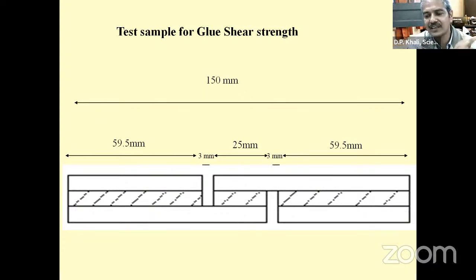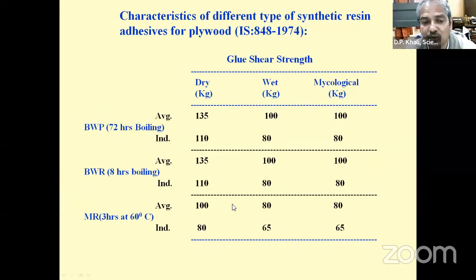In the previous slides, I showed you the glue shear strength between those two dots. The sample is fixed, and then a gradual load is applied to see how much load the sample is able to withstand. If the average is more than 135 in the dry condition, then we can say that this adhesive meets the criteria of BWR. Now, what do average and individual mean? As you all know, wood is a biological material, so to cater for the variability, at least 6 samples are tested. The average of 6 samples should be more than 135.